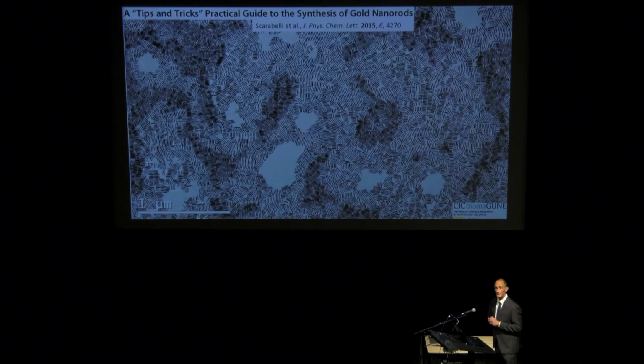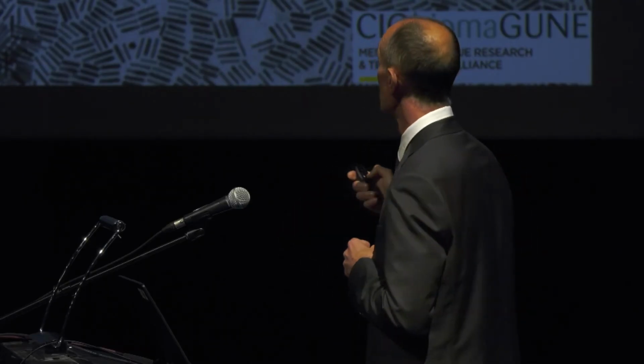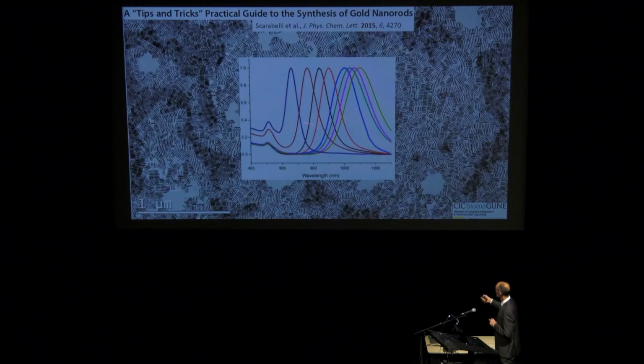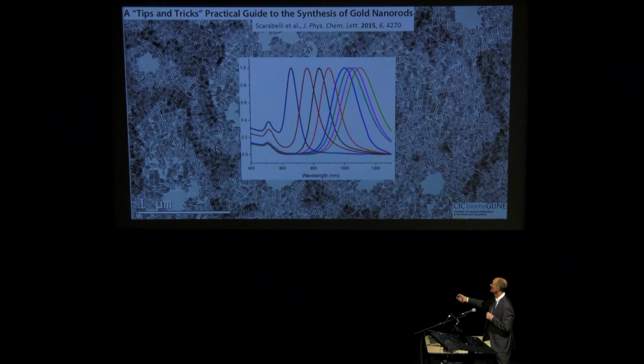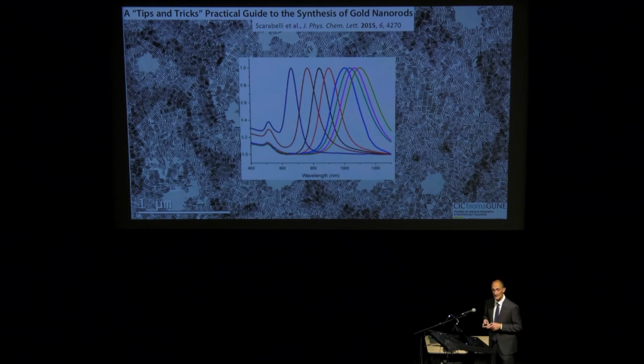So by exploiting all these concepts and using all these parameters, we are now able to make almost routinely dispersions of nanorods that look like this. And we can make them in a way that we can control the aspect ratio and tune the plasmon resonance, as I showed you earlier. However, if you compare any of these spectra with the calculations for one single nanorod with the average dimensions of what you see here, you find that these spectra are still broadened. And this is because in a colloidal dispersion, it's almost impossible from simultaneous growth to obtain a completely monodisperse system, with all the particles being identical. And this is why you get an average contribution to the optical signal.